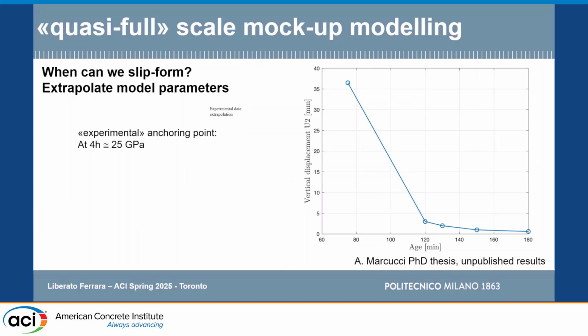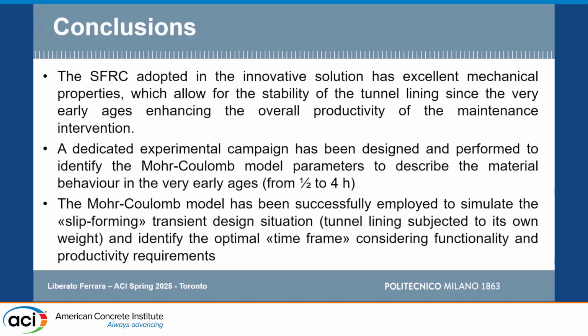But then, in the end, we wanted to see, okay, but when can we really slip form? When do we really have displacements that can be accepted? Obviously, if you perform an elastic analysis, you will always have a displacement if you don't anchor, because it's there. So we extrapolated and merged the results at the very early ages, up to 2 hours, with the one that we had at 4 hours to find the transition function. And we realized that, for example, at about 2 hours, we have displacement in the range of 2 to 3 millimeters, which is deemed to be satisfactory and acceptable for the productivity of the technology.